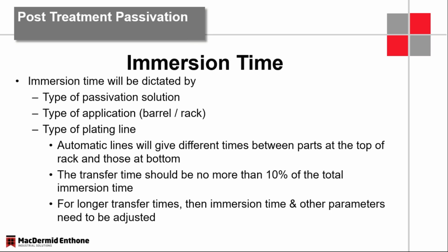The one thing that's interesting and good about the three things I've talked about: concentration, time, temperature, concentration can go to pH, is that you can play one against another. If you have a time where you're locked into 40 seconds, but you need to develop a thick film that would normally take 60, 75, 90 seconds, you can lower the pH. You can change the concentration. You can increase the temperature. So you can play these parameters off of one another to fit the line and the application that you are dealing with. So although these are rules and need to be followed and are somewhat rigid, they are adaptable and can be played one against another.